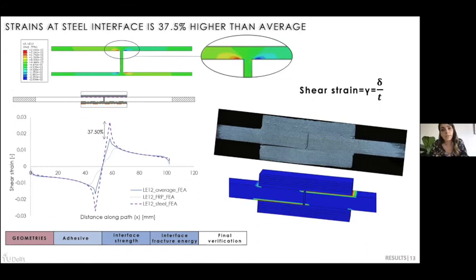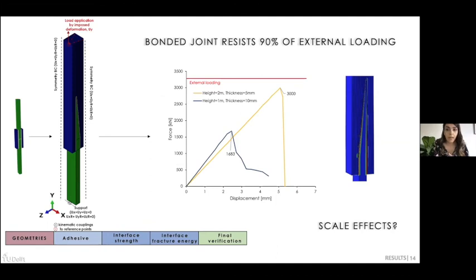Then I did an extra verification going back to my finite element analysis, where I asked the software to show me the highest shear strain concentrations, and it was proved that these were around the steel to adhesive interface instead of the FRP to adhesive interface. I had everything, so applying the current set of bonded parameters from the small scale joint to the larger scale resulted in a connection that can resist up to 90% of the external loading. I also checked if scale effects exist when upscaling a bonded joint, but unfortunately I cannot elaborate on that right now. Just keep in mind that the scale effects do exist.